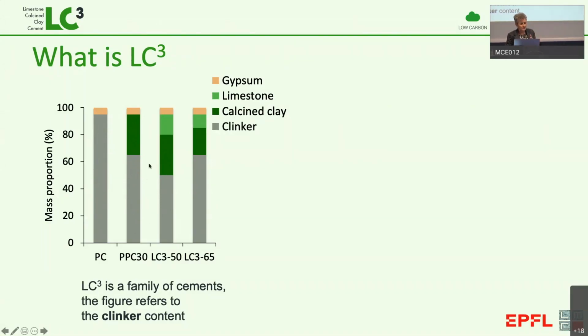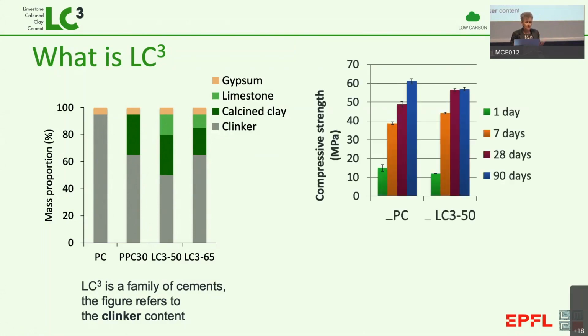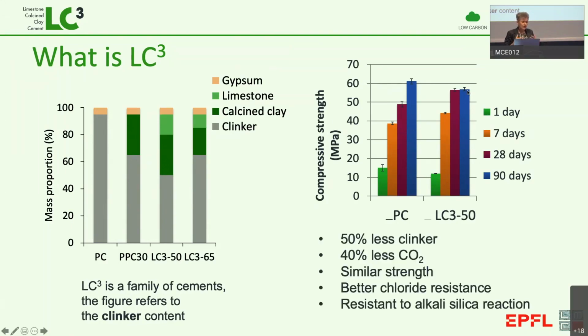Now, in LC3, we can take out another 15% of that very high CO2 emitting cement and replace it with limestone. And limestone, if it's just ground up, it's not heated, then it's a very low CO2 material. And with this, we can gain similar strength to the reference Portland cement. Slightly lower at 1 day for this experiment, but you can actually bring the strength back up even at 1 day by grinding and other technologies, and by 7 days it's stronger, 28 days it's stronger. So here we have 50% less of the Portland cement.